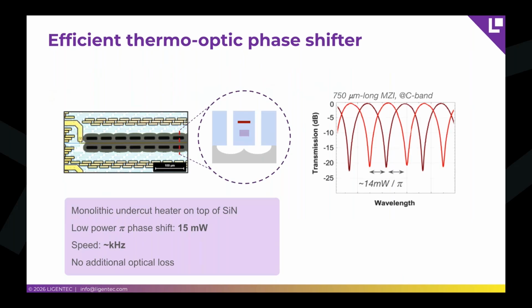One low loss modulation or phase shifter integration is a heater where the waveguide does not interact with the heater material, and so the losses are not influenced by the heater material. And here we have a structure that can reach very low pi phase shift powers down to 15 milliwatts, keeping a speed of kilohertz for the switching speed in these